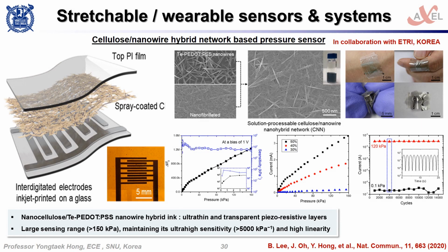Recently, we demonstrated with ETRI a technology for an ultra-thin, wide pressure sensing level, ultra-high sensitivity resistive sensor with high linearity. Contact areas of the cellulose nanowire hybrid network change under pressure, resulting in such an ultra-thin performance sensor.